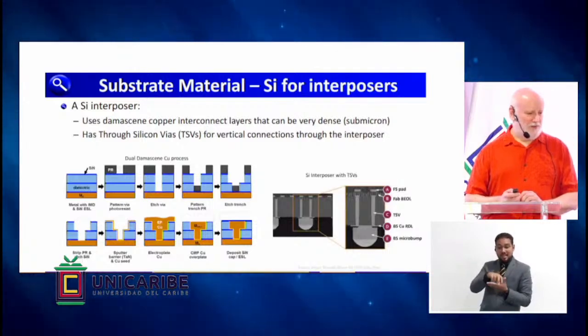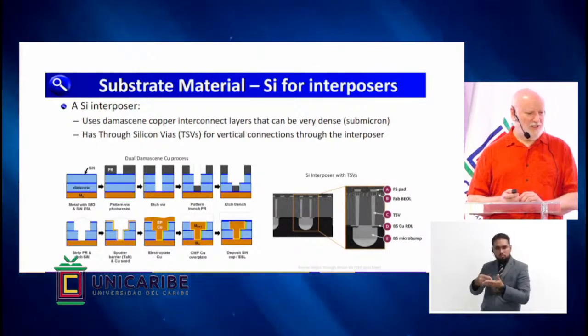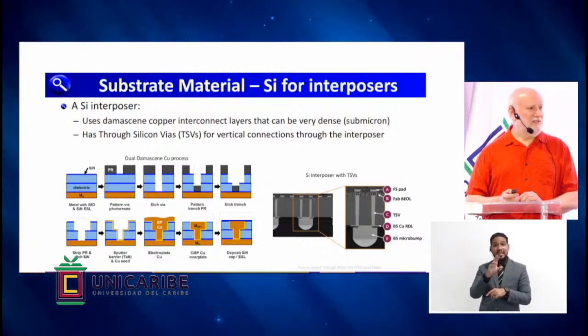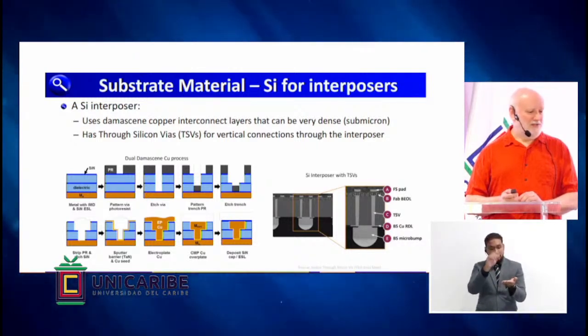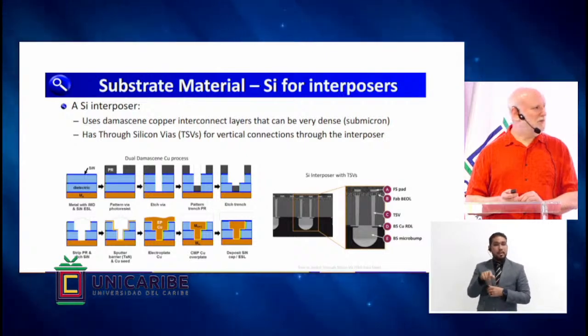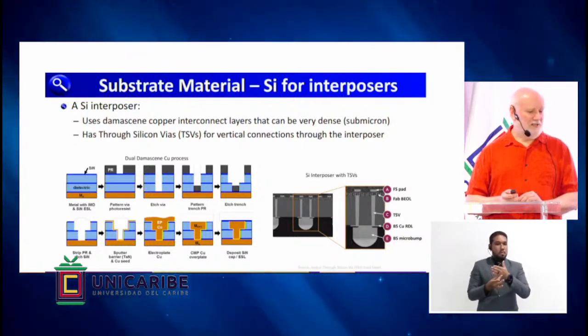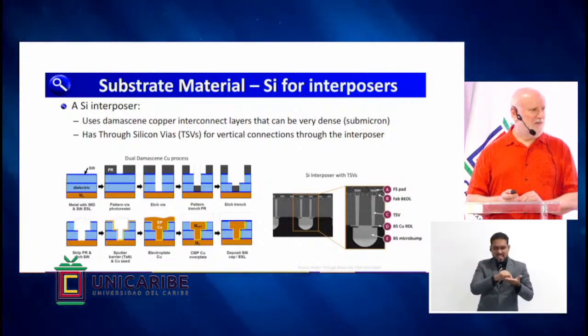So silicon is the material of choice for interposers. The interconnect is a damascene copper, so it's copper that's inlaid into etched trenches in the dielectric layer. The other significant feature is what we call a through silicon via, or TSV. This is a specialized deep reactive ion etching, or dry process, sometimes called the Bosch process because it was developed by a company named Bosch, that cuts all the way through the silicon wafer from the front side to the back side.